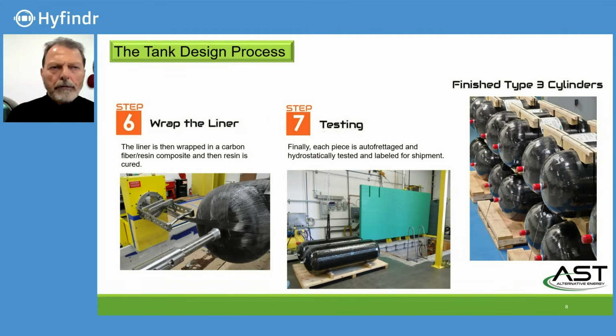The autofrettage testing lays the aluminum into the carbon fiber. The carbon fiber has a very low elongation, about 2 to 3%, while the aluminum 6061 has an elongation between 12 and up to 16, 18% in different cases. So the aluminum is stretched into the carbon fiber under high pressure, and then the hydro test brings it back to the original form. And there, the liner will cycle between those two areas for its cycle life of 15 years in the case of the hydrogen cylinders for high pressure.